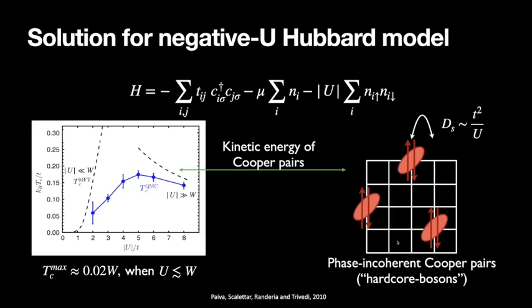So in fact, if I were to go back and think about what's going on here, it turns out in this regime, what's limiting TC is really the phase ordering scale. Okay. And so how do we think about that? Well, it turns out for this problem, in this extreme regime of a large U over T, I can just start from the strong coupling limit. Okay, so I can switch off my hoppings altogether. First, just try to solve this problem.